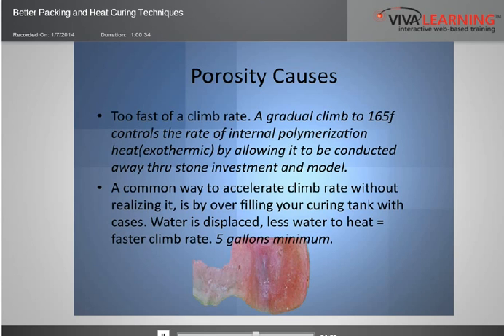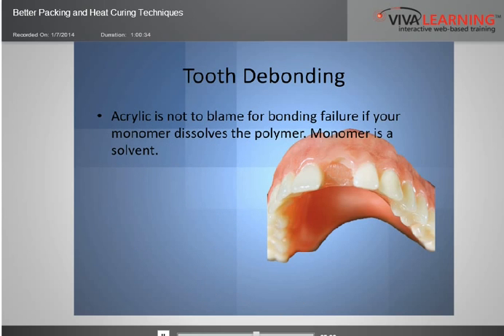Here's one. I love it. Teeth bonding. Acrylic is not to blame for bonding failure, folks. I get these calls, something's wrong with the acrylic. My teeth are not sticking to the acrylic. It's got nothing to do with the acrylic. Monomer is a solvent. You know, that's why when you add powder to the liquid, the powder turns into a doughy mass. It turns into a doughy mass because the solvent action of the monomer is breaking down the powder. It's that same solvent action that creates a better bond on teeth.